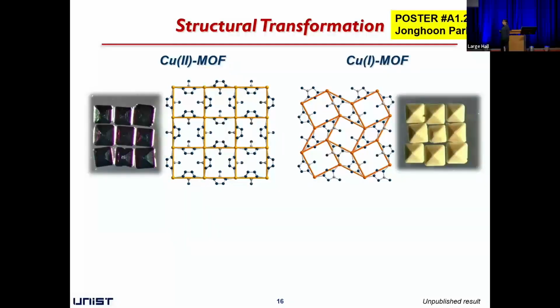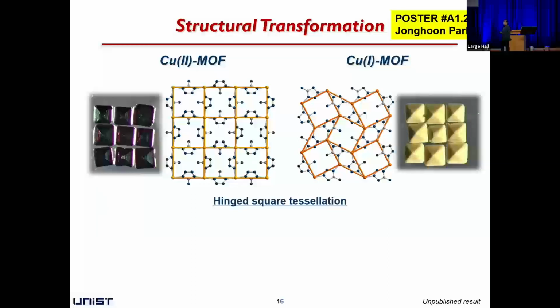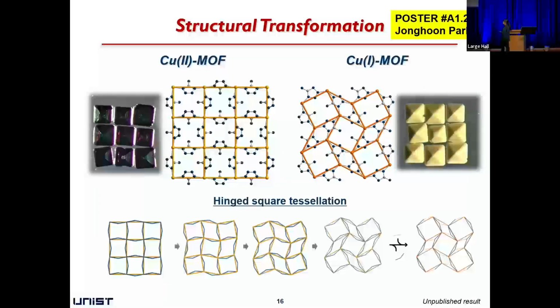Just by simple heat treatment, we could obtain the copper-1 MOF. The crystallinity is still retained, and all the copper-2 is transferred to copper-1. And we can see the structural transformation, and this structural transformation can be explained by hinged square tessellation. Also, this topic will be presented by my student tonight. So if you are interested, please visit him.